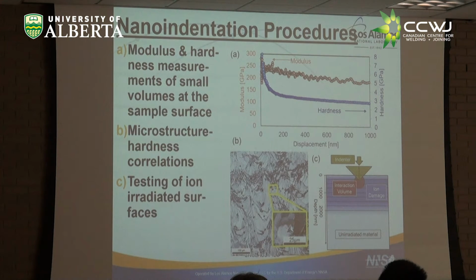And the third and most important reason is if you stick it into the reactor and it gets activated by neutron irradiation, you probably can't touch it for the next 7 years. So it's probably not a good idea to do a PhD on this unless you want to stay around for a long, long time. So you can't get to the parts or the components then. So the ion irradiation, the downside is that it's not a very deep layer of irradiation damage. So you can actually do ion irradiation on surfaces and then look at other regions and compare the hardness, and look at ion irradiation induced damage like we spoke about earlier, and see changes in hardness which will manifest themselves in properties in service.